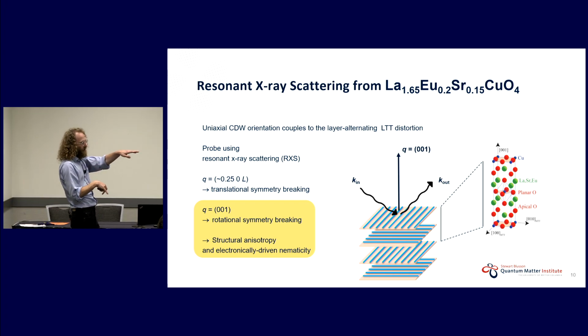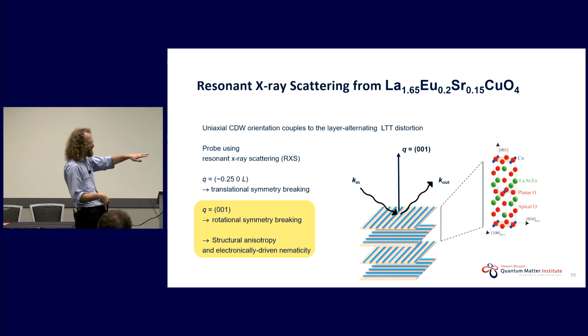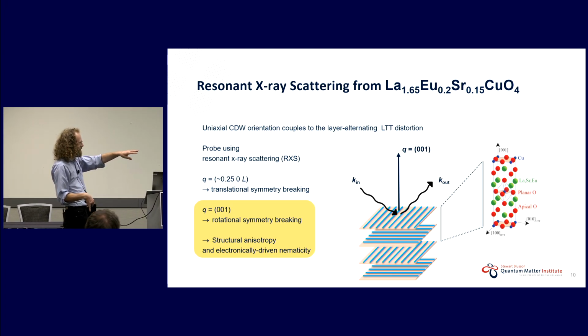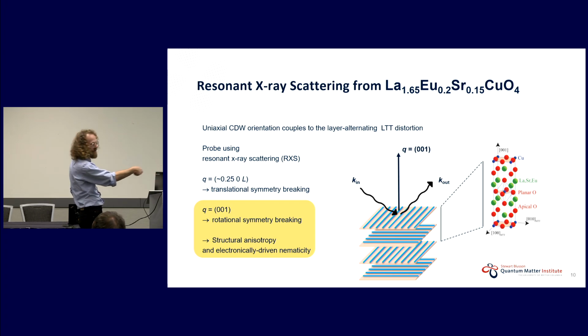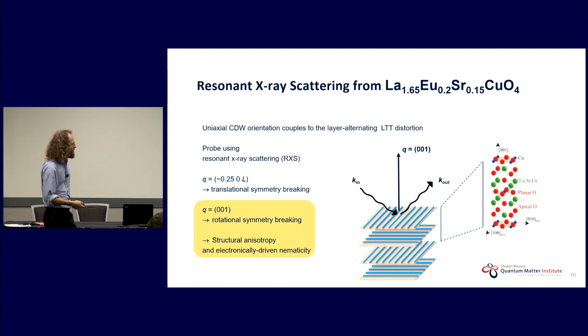Because the copper, if you go to the copper L3 edge, the low energy states are now anisotropic, and that anisotropy is rotating as you go up, okay? And the same is true if you go to the oxygen. And now, the particularly interesting thing here is that